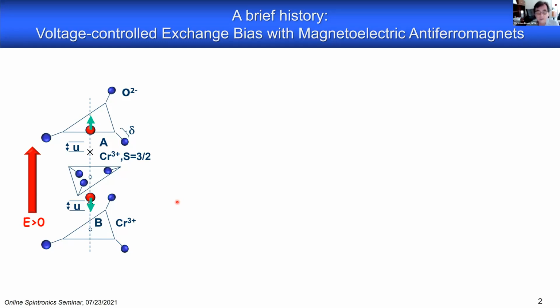What it, globally speaking, does, it lifts the degeneracy of the sublattice magnetization, and so you no longer have a fully compensated antiferromagnet. You have a type of a small ferromagnetic moment, and in the linear regime, that means the magnetization induced by an electric field is mediated here by this magnetoelectric susceptibility. Now, the sign of this magnetoelectric susceptibility depends on the domain state in which the system is. There are two 180-degree degenerate antiferromagnetic domain states. And in one of them, the sign of alpha is positive, and in the other one, the sign is negative. So that means that the magnetization you induce in one domain is positive, in the other domain it's negative.